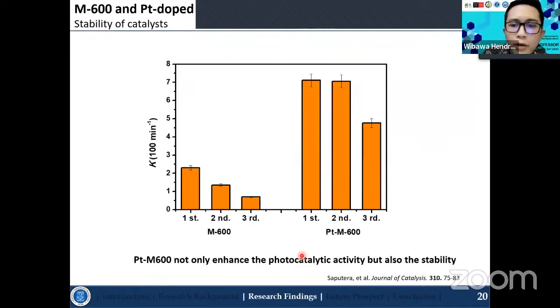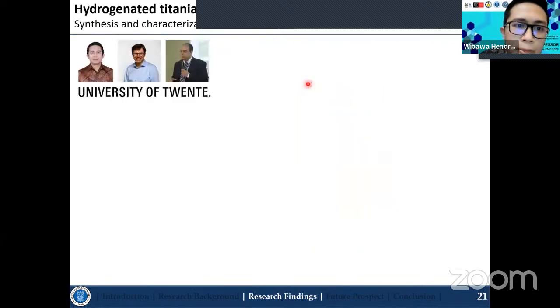And I also did the stability of the catalyst. Yes, for the M600 it gradually decreased, but for the platinum dope on M600, for the second cycle it is almost the same. There is no significant decrease, but for the third cycle, it decreased up to 1.4 times compared with the first and second cycles, indicating that by using the metals dope on the M600, it will enhance not only the photocatalytic activity, but also the stability of the catalyst.